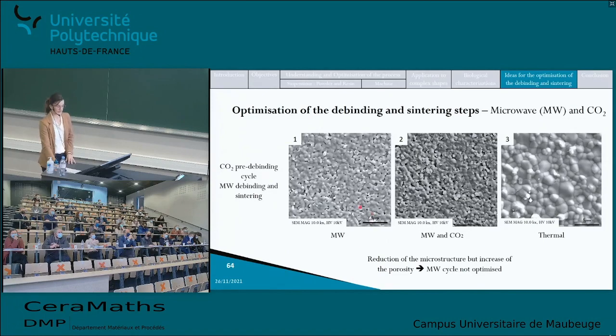And also it's possible to see here that the use of the microwave could enable a reduction of the grain size of the sample and therefore improve the mechanical properties. So this was more of a proof of concept that the microwave debinding and sintering cycle could be used in combination with the SLA process. However, there is still a lot of improvement to be done on this technique and a lot of optimization on the thermal debinding and sintering cycle, microwave, sorry.